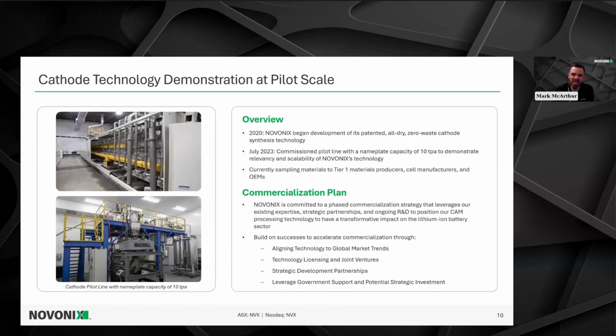So this slide really illustrates an overview of what we are doing today. On the left-hand side of the slide, I'm showing some photographs of inside our pilot facility. The top left photograph shows our pilot scale roller hearth kiln, or RHK. It's a 13.5-meter long device with many, many heating zones to very adequately control the heating profile during calcination. And in the lower left photograph, I'm showing our 70 kilogram per hour pilot scale jet mill, which is housed within our 1,200 square foot dry room with an average dew point temperature of roughly minus 50 degrees Celsius on a good day. There's also some other assets that are inside of that dry room displayed in front of the pilot jet mill.